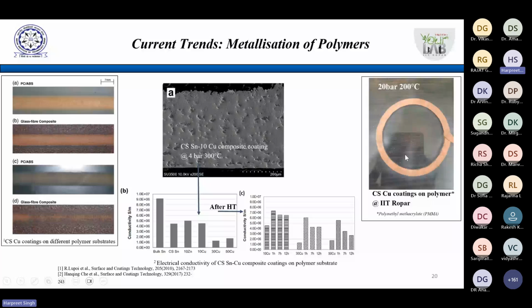This is a copper ring made on a polymer, which is PMMA polymer. We have deposited this coating, right? So this kind of work can be used for making some electrical circuits on certain polymer substrates and so on, right? This is another study where the electrical conductivity of a cold spray copper composite coating on polymer substrates has been measured.